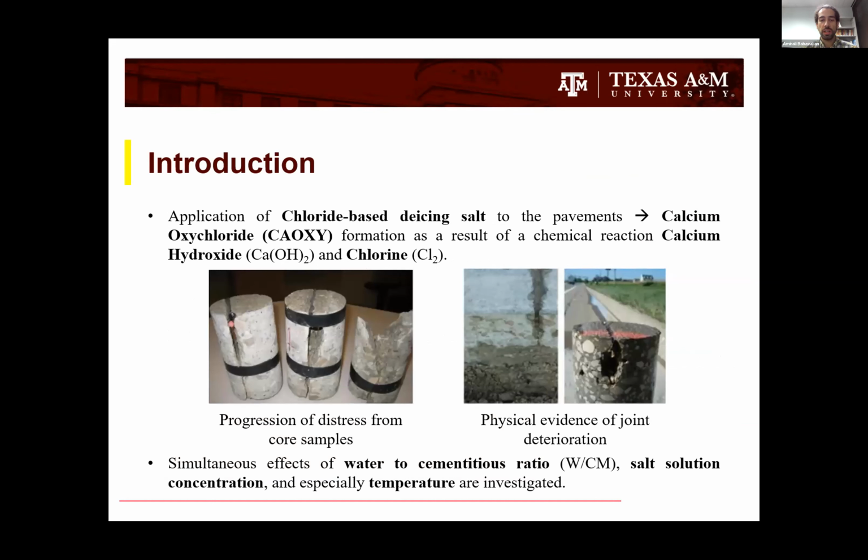In this picture, you can see different physical evidence of joint deterioration and progression of distress from core samples from the fields on concrete pavements. As I've mentioned, this deterioration is because of the formation of calcium oxychloride, or CAOXY, as a result of chemical reaction between calcium hydroxide and chlorine. Chlorine is coming from chloride-based de-icing salts such as sodium chloride, magnesium chloride, and calcium chloride.